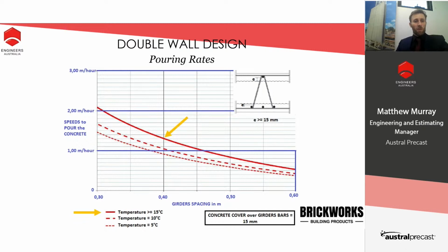Pouring rates. With every site, every contractor wants to fill the panels as fast as possible. And the major thing that dictates this is the capacity of the girders to withstand the hydrostatic pressure of the concrete on site. Here we can see the girder spacing ranging from a minimum of 300mm up to 600mm. 300mm is the minimum spacing that we do for the girders for double walls as per the European regulations, and a maximum spacing of 600mm.